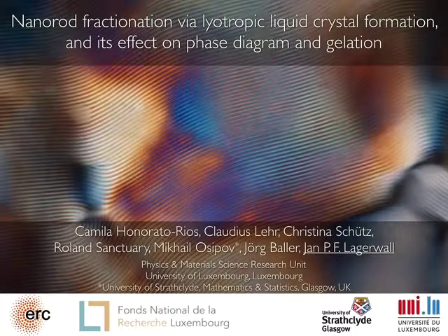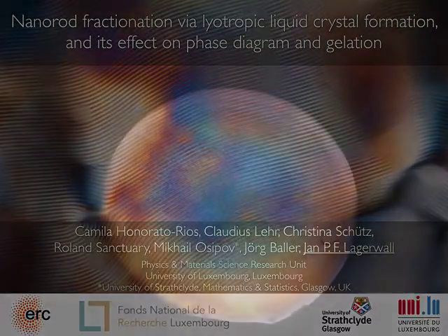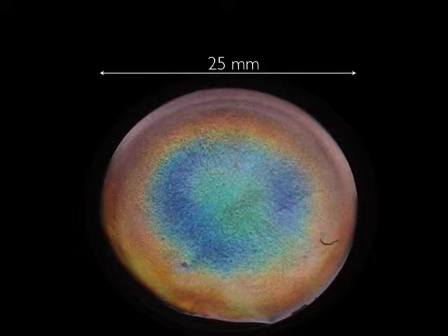In principle, what makes people interested in these is that you can make functional materials from them, such as this film. This is basically paper, photonic crystal paper, if you like, that is prepared simply by taking a suspension of cellulose nanocrystals, putting a drop on a glass slide, and letting the water evaporate. And the colors you see are structural color, so the colors are there because of a periodic structure within the film that these nanocrystals have formed.